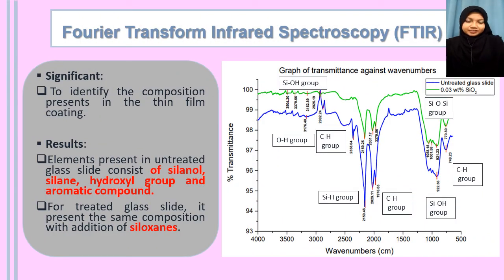Okay, the thin film coating is characterized by using Fourier transform infrared spectroscopy. The significance of this characterization is to identify the composition present in the thin film coating. So as a result, the elements present in the untreated glass slide consist of silanol, silane, hydroxyl group, and aromatic compound. As we know, the silanol and hydroxyl group have an OH bond that will contribute to the hydrophilic properties. Meanwhile, the aromatic compound contributes to the hydrophobicity properties.